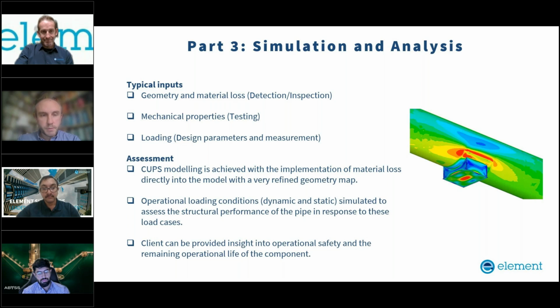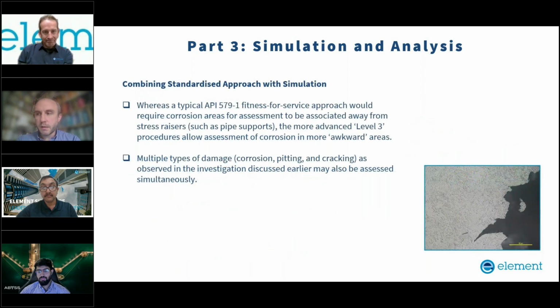So we're able to bring all that damage morphology, a good validated representative approach to what loading conditions are actually being seen through operational conditions, and simulate what the response of the component was to those loads. So that actually tells us a great deal about whether or not those areas of damage that have been seen are safe to remain in place, perhaps until a more convenient time for a shutdown, such that we can minimize the amount of maintenance, the amount of shutdown time on the plant.